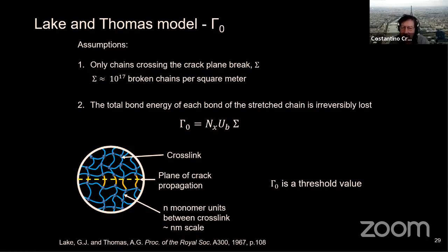But there are a number of assumptions there, in particular the localization, that you only break this yellow chain and you don't do anything to the environment, which doesn't seem very realistic. But it gives you a pretty good value, which is close to experiments, and also has the right scaling. So this model still has very much value in terms of predicting experimental results. But it doesn't look like the molecular picture is consistent with what we see. We see something much less localized than that. But we can compare with that.